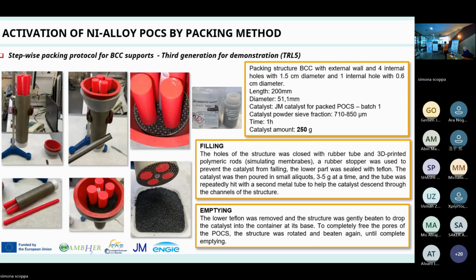Another thing that we are exploring in AMBHER is packing. In this case, the partners prepared similar catalyst with the required size fractions for packing. The main difference is that in this case we can charge 250 grams of catalyst against 50 grams, with a simple packing procedure, not so complicated.